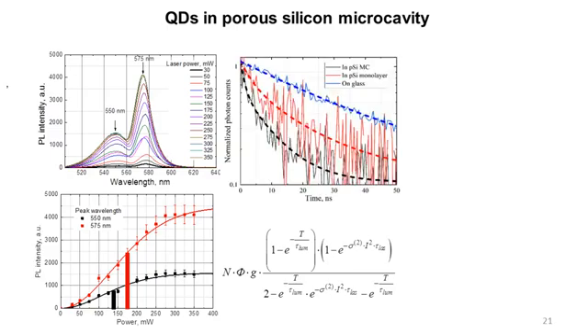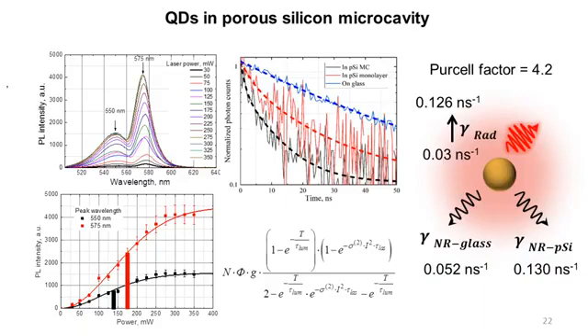Quantitative estimation of the Purcell factor could be made by comparing the radiative relaxation times extracted from the photoluminescence kinetics of the quantum dots coupled to the microcavity resonant mode and the uncoupled quantum dots ensemble. In order to exclude the influence of the non-radiative relaxation pathways arising from the interaction of quantum dots with the surface of porous silicon, a control experiment has been made. As control samples, we used quantum dots embedded inside the single Bragg reflector and quantum dots dispersed in the polymer matrix on a glass substrate. The total radiative and non-radiative relaxation rates were calculated. Using the final values, we can estimate the Purcell factor, or the radiative rate amplification factor, as 4.2.